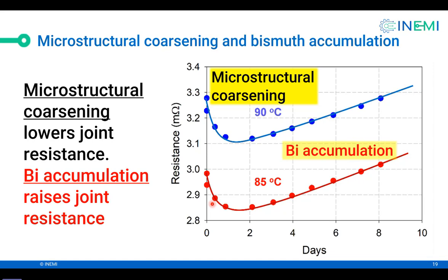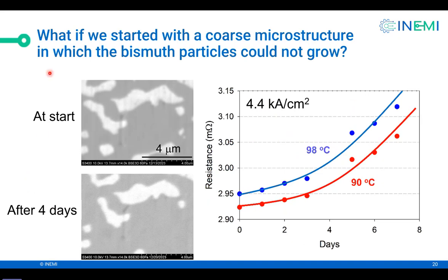Now, what if we began with the coarse structure to begin with? So let's say we anneal a specimen and we coarsen the structure. So you can see, again, the bright region is bismuth rich, the gray region is tin rich. Now we do a 4-day experiment. The microstructure barely changes, and you can see that there is no dip in the resistance. Resistance keeps going up. So this is additional proof that it was the coarsening of the structure that caused the dip. So keeping that in mind, we made sure that we don't get confused by that dip in the resistance, that we wait for the curve to start going up before we make electromigration measurements.